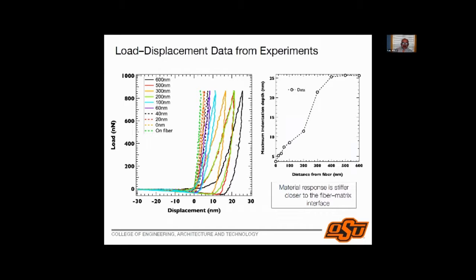There's one more thing that happens which doesn't happen in regular indentation: when I unload, I will see that my load goes negative, because as I'm pulling the tip out, there is some adhesion happening. The polymer sticks; the polymer doesn't want to let go. That's why we get some negative loads over here. This is the adhesion effect, and the difference over here is the difference between elastoplastic deformation and purely elastic deformation. But as a first step, we are only interested in the elastic properties.